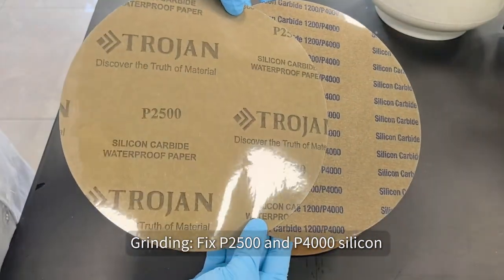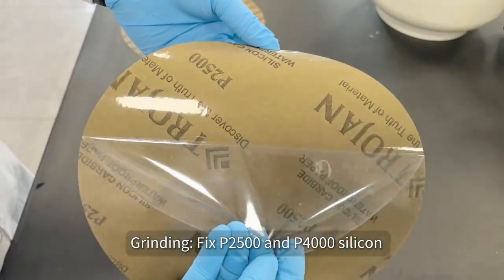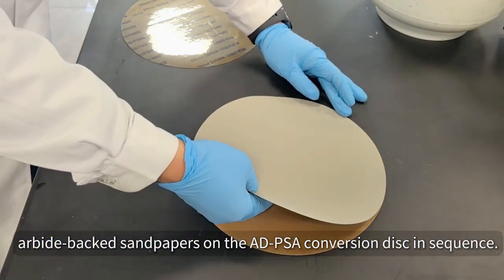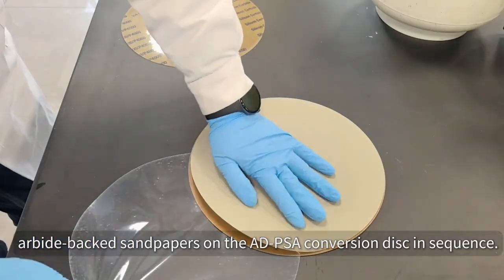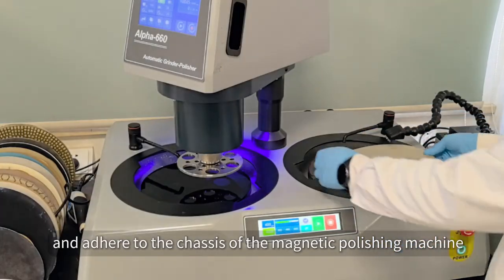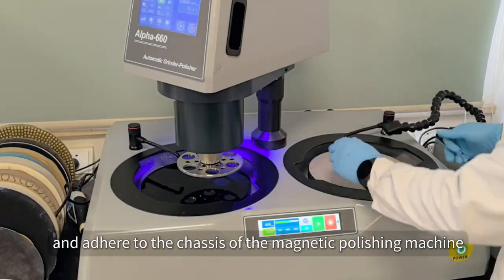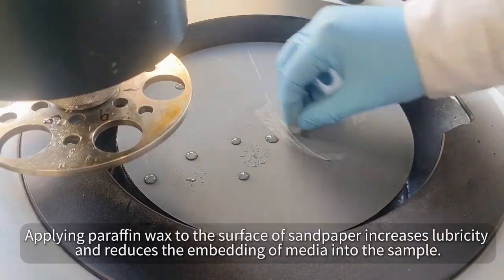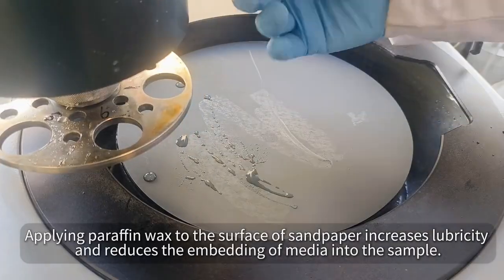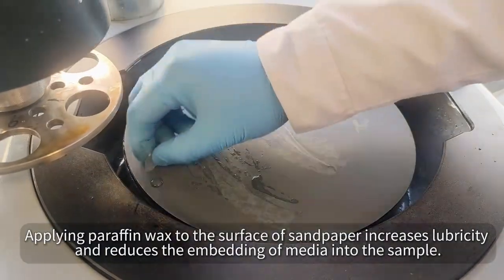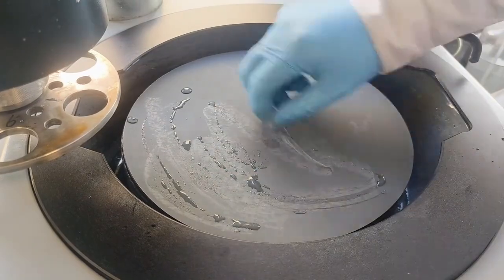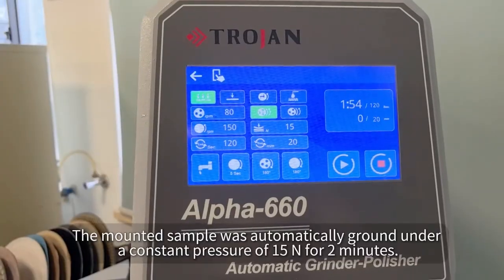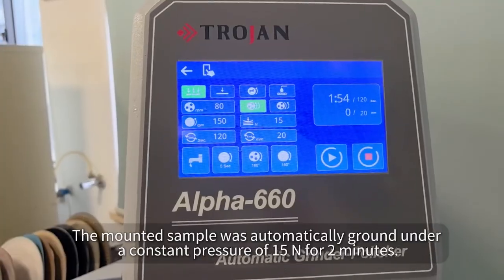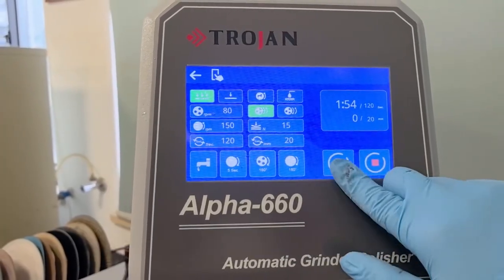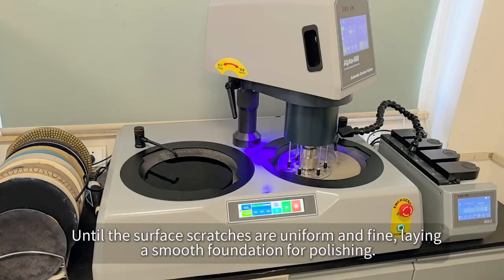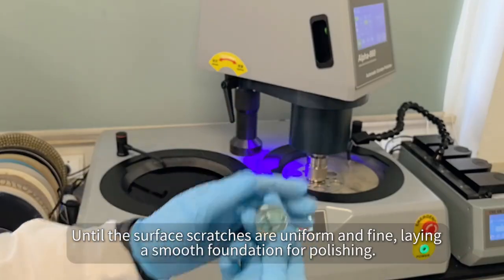Grinding. Fix P2500 and P4000 silicon carbide-backed sandpapers on the ADPSA conversion disc in sequence, and adhere to the chassis of the magnetic polishing machine. Applying paraffin wax to the surface of sandpaper increases lubricity and reduces the embedding of media into the sample. The mounted sample was automatically ground under a constant pressure of 15 N for 2 minutes until the surface scratches are uniform and fine, laying a smooth foundation for polishing.